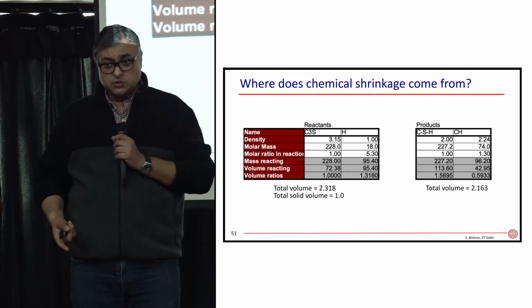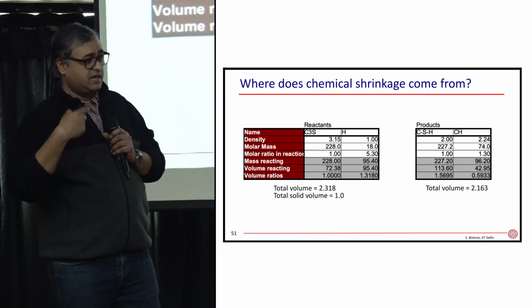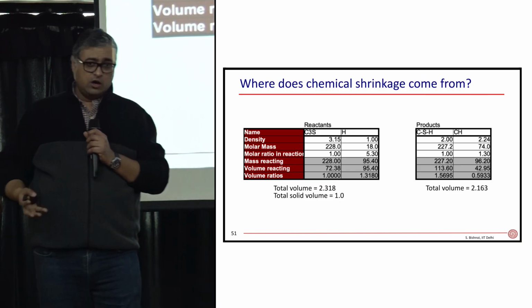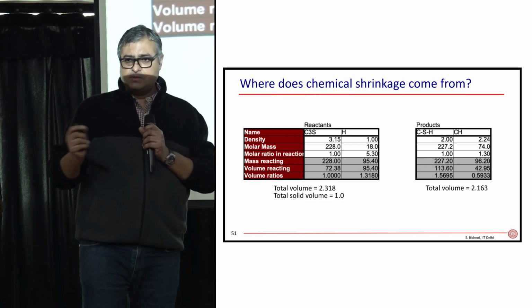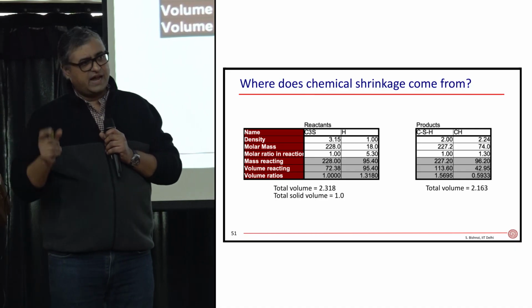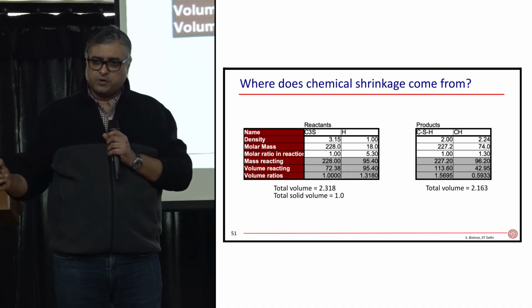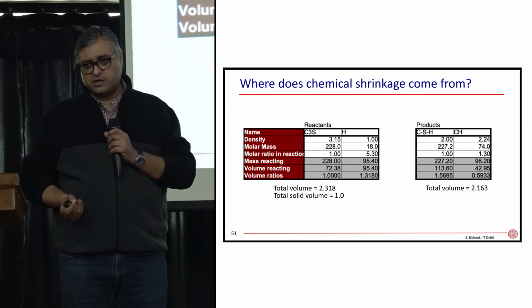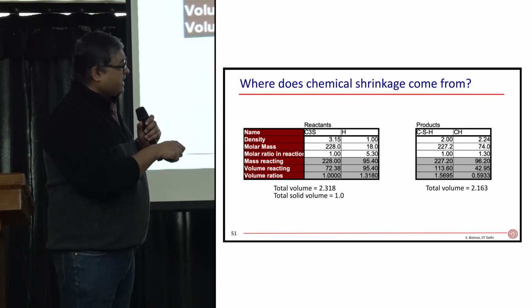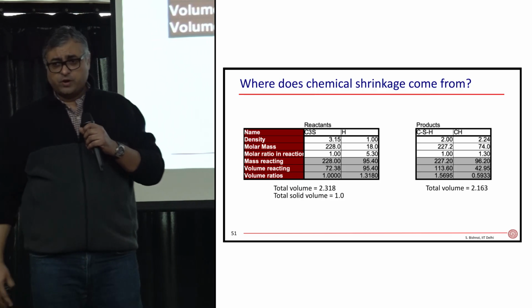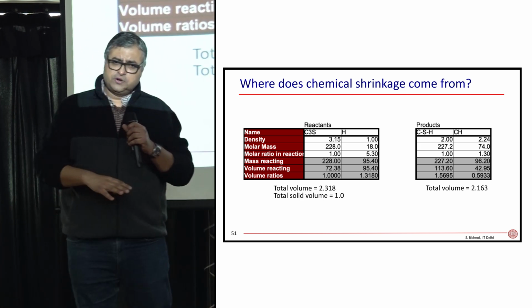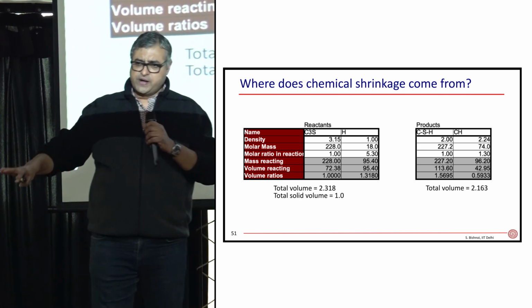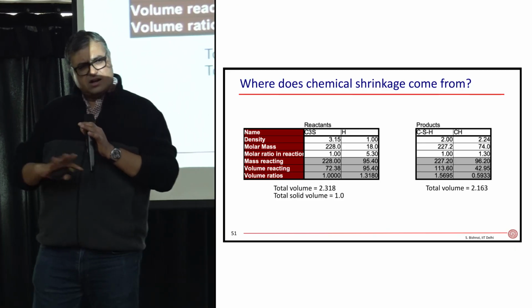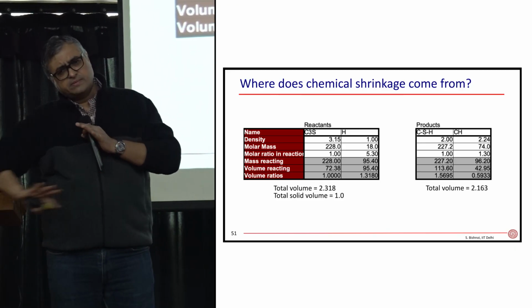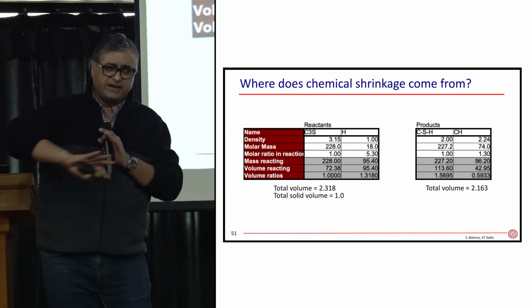There are other reactions as well - there is the reaction of C2S, there is the reaction of aluminate and all of it, but those numbers are also very similar. For an overall cement, for the reactive part, this number varies between 0.4 to 0.45 if you calculate that. So at a water binder ratio of around 0.42, you have just enough water to react with all the cement, just enough cement to react with all the water. Theoretically, not practically, theoretically all the cement can react with all the water. There should be no unhydrated cement left.